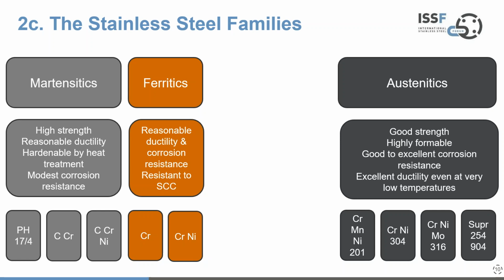And people will be familiar with these in the forms of cutlery, pots, pans, domestic appliances. But these products have really good strength, they're highly formable, good to excellent corrosion resistance, and they have excellent ductility, even at very low temperatures. These products do not suffer from a ductile to brittle transition as temperatures fall. And there's a broad range of products here with chromium manganese nickel steels, straight chromium nickel steels, which people will have seen as the 18/8 or 18/10 stamped on cutlery or domestic goods.